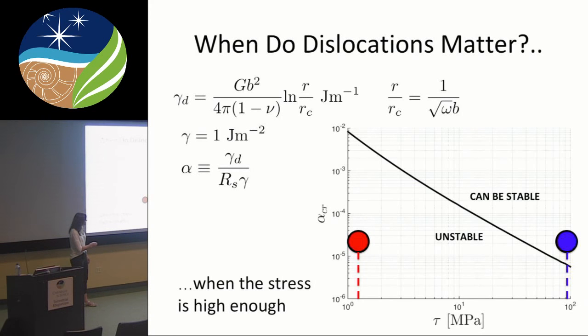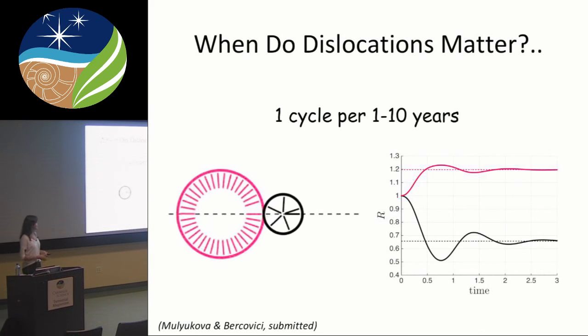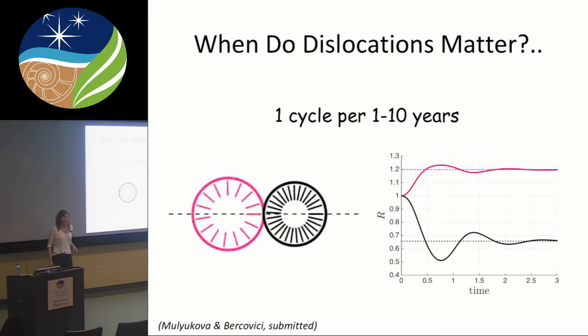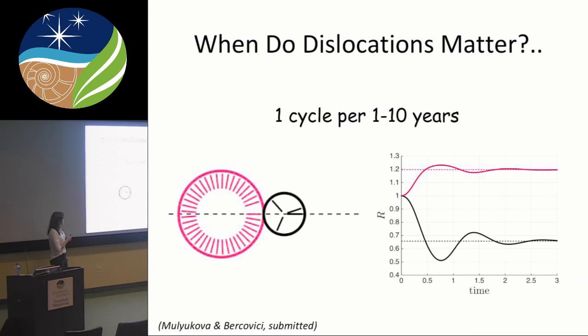And at these stresses, we should now be thinking about the physics associated with the dislocations to determine the grain size. This is, again, taking this model and inferring stress from some of the materials. And the second implication of the study, this is coming back to the earthquake cycles that we briefly mentioned before. So I showed you that for certain conditions, the system can oscillate as it reaches its steady state. And for olivine-like material, again, using the same parameters as before, the timescale of the oscillations will be something like a cycle per 1 to 10 years. So this is, on geological timescale, something that will be relevant for maybe an earthquake cycle.